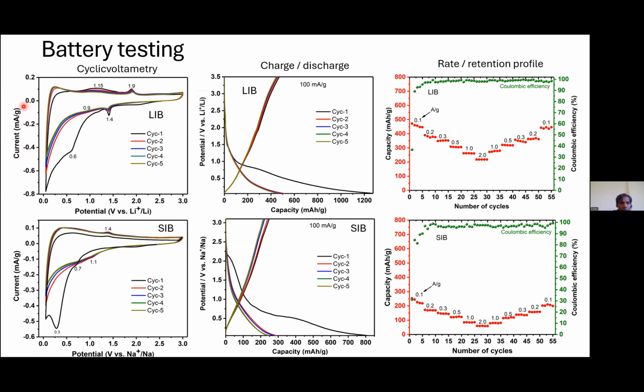And what about the current response? And what is happening? What kind of electrochemical event is happening at what potential range? All this information can be explored from that. The history of the material can be predicted. So by looking at the cyclic voltammetry, we feel that it's a very good rechargeable battery. And then the charge discharge profiles were evaluated. As you can see, very good consistency, with capacity closer to 500 milliampere hour per gram. Remember that for natural graphite, 372 is the theoretical capacity, but experimentally you end up between 200 to 300. And now you have very good capacity with consistency, right?